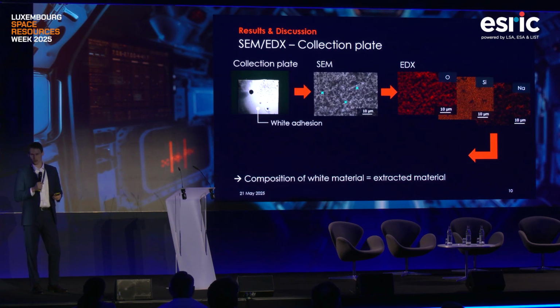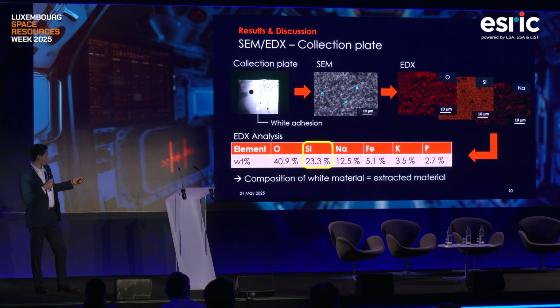That leads us to the last analytical method, the SEM EDX of the collection plate. What we adhered to the plate is a white, finely grained powder, notably white, very different from the Mars simulants. The SEM shows a very homogeneous adhesion at micrometer scale, and the EDX point analysis and mapping shows us that we have a composition as shown here. Actually most of the metallic component is silicon. This is very interesting because we can extract one of the major components of regolith and really refine regolith into multiple feedstocks. Most importantly here being silicon, and additionally also the alkalines and iron apparently, and phosphorus.